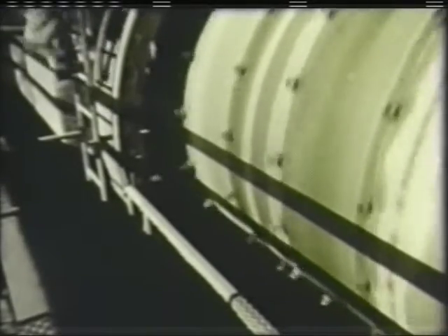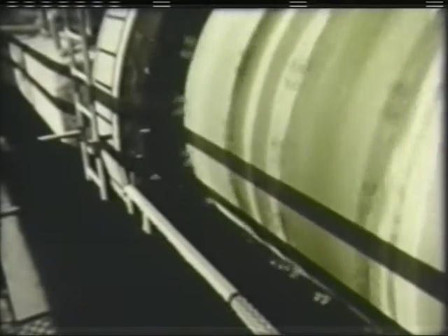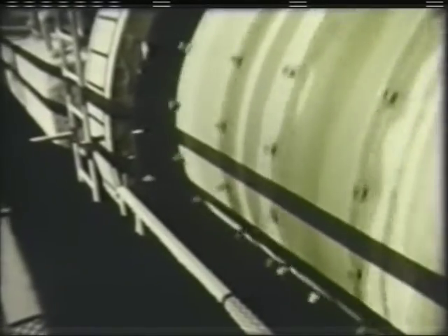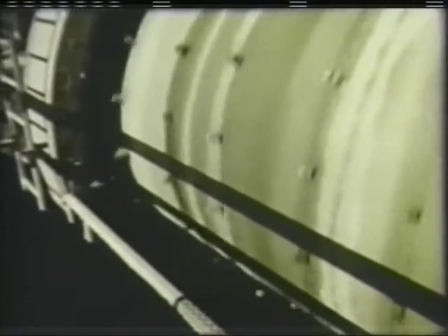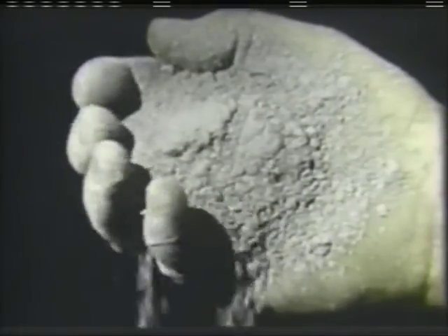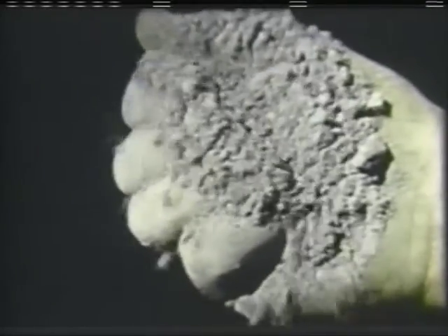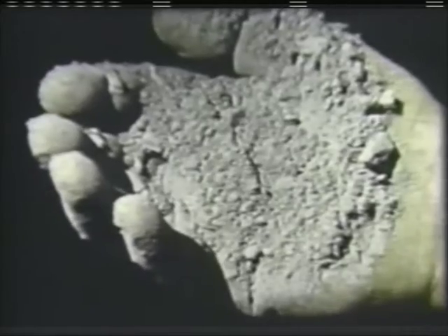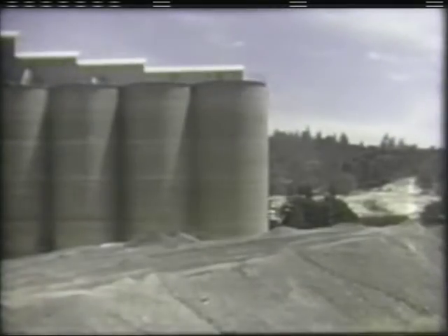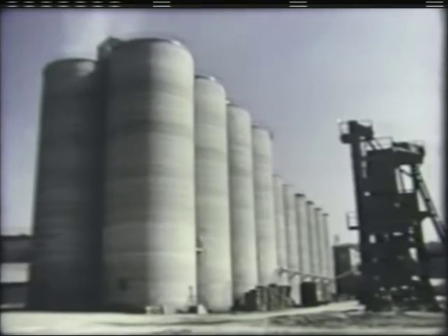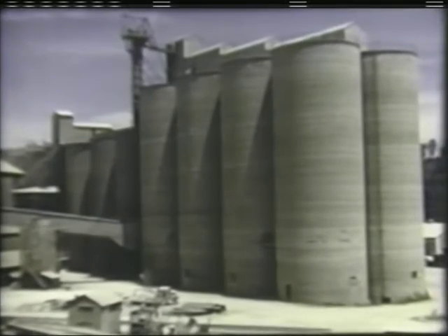Next, the clinker goes into the finish mills, which are similar to the raw mills. Here, with the addition of 3 to 4% gypsum, it is ground as fine as flour by the action of the tumbling steel balls. This is cement, produced at this plant at the rate of 4.5 million barrels a year. It is pumped from the finish mills to one of 20 storage silos, holding a combined total of 400,000 barrels of cement.